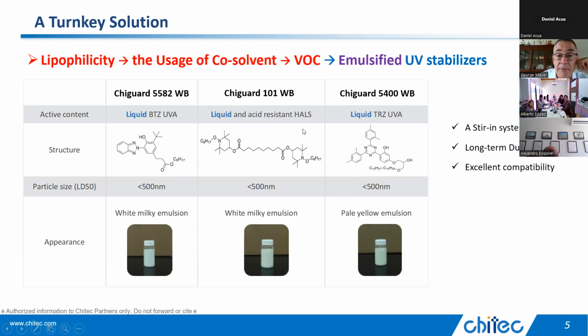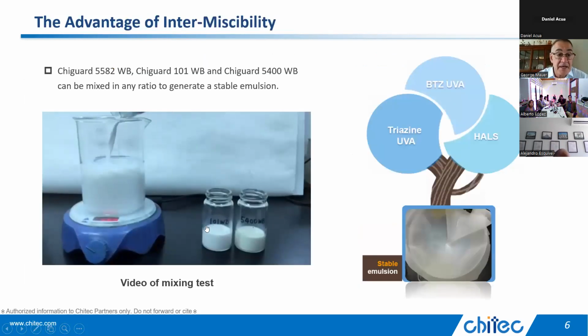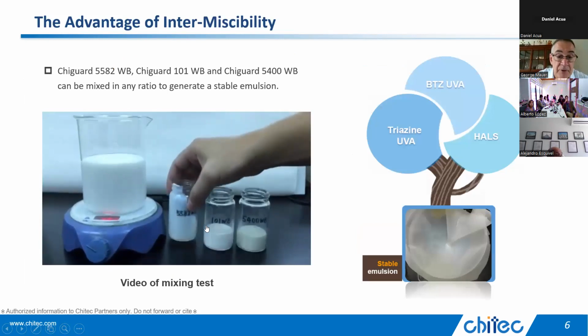The ChiGuard 101 WB is a hindered amine light stabilizer. It will take care of the radicals that are formed, and it is non-basic, so it won't interfere with a cure if it's an acid-catalyzed cure or something like that. It's also a nice emulsion. All three of these are very nice emulsions that can just be added in, one, two, or three of them. Actually, some customers do one to one to one, which is a pretty smart approach. One percent solids on solids of each of these is an excellent starting point. It gives you outstanding performance.